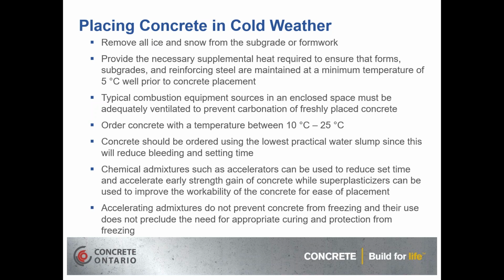We have a calcium chloride accelerator, which is very common and effective in winter construction. However, given the chloride component of the accelerator, it is not recommended for reinforced concrete that contains steel or rebar, and as such, the equivalent accelerator for that is a non-chloride accelerator, in particular in reinforced concrete elements where corrosion is a concern. However, with the accelerators in the concrete mixtures, we need to be mindful of the fact that they do not prevent concrete from freezing, and their use does not preclude the need for appropriate curing and protection from freezing. Concrete is not antifreeze. It will freeze if it's not adequately protected from freezing.